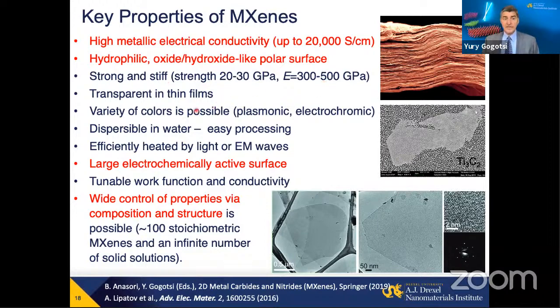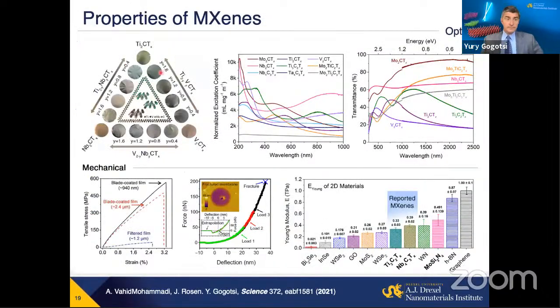But also, they provide a variety of colors because they have plasmonic properties here. You have seen MXene solutions and films of several colors on the front slide when I showed you initially. And of course, you can control it by controlling the composition. Those are UV spectra you can see here. And this goes actually now into the IR to about 2.5 microns.